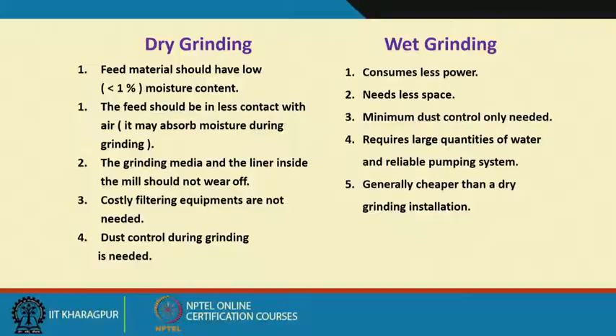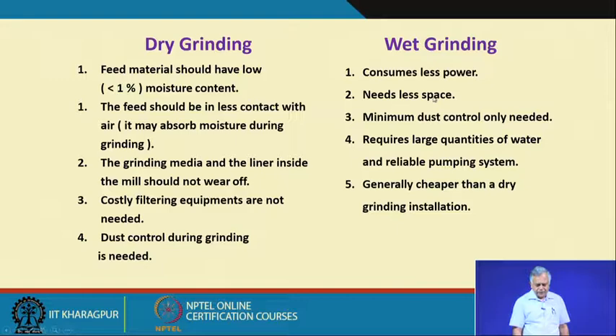And then the materials are free flowing, and they are dispersed within the mill. When they are dry, many times they may start getting agglomerated because of the new surfaces created, and you have to again break this agglomerate unnecessarily. So, this is the reason why wet grinding normally consumes less power in comparison to dry grinding. It needs less space also, because you do not need dust control devices, and only minimum dust control is needed. But it requires large quantities of water and a reliable pumping system.